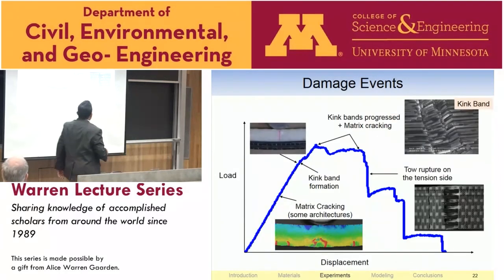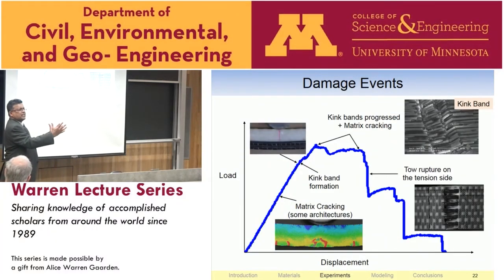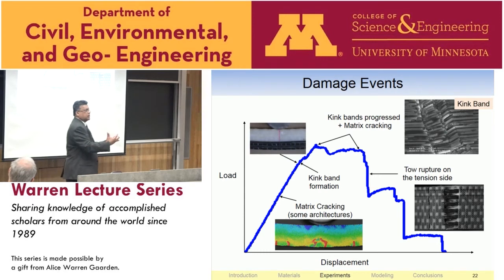So the events are like this, right? I just captured schematically what happens in these materials. You get a linear sort of response governed by the geometry and the stiffness. Then you get this matrix cracking at the beginning, but still the load's increasing. Then you get the shear band or the kink band forming, and then the kink band does work progressively. That controls the plateau. And then you get a total load drop when you get tow rupture on the tensile side of the specimen. So it's compression, tension, shear all in one specimen and one structure.